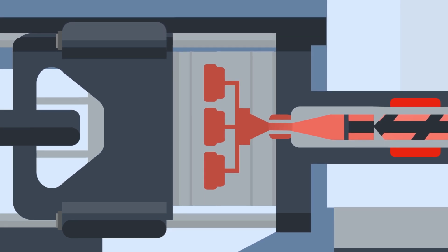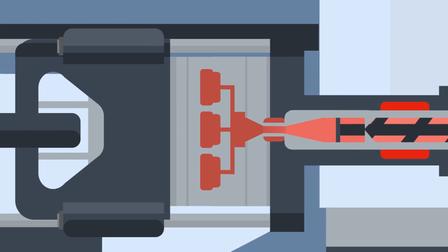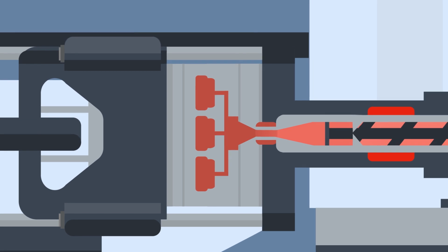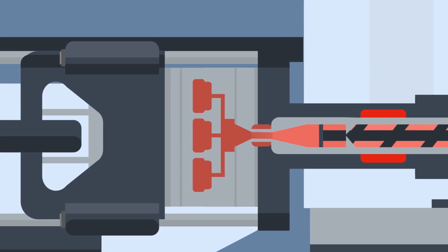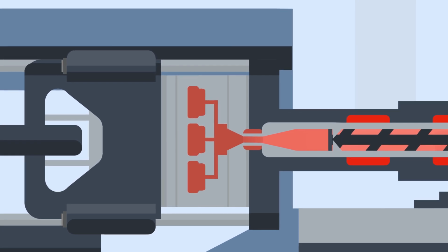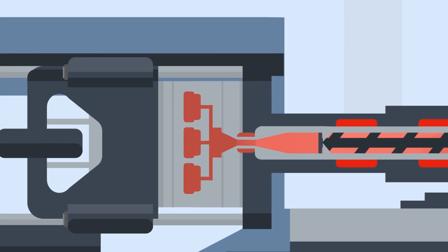pressure into the cavity. A gate inside the tool helps to control the flow of the plastic. When the tool cavity is mostly full of liquid, a holding phase begins, where the part starts to take its final form. After a set holding time, the screw will screw back to its set point. This happens at the same time as the cooling phase of the cycle.